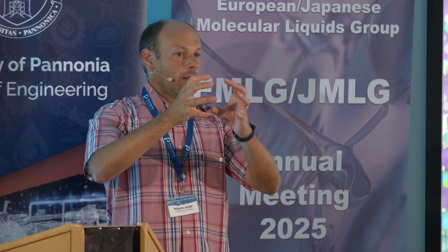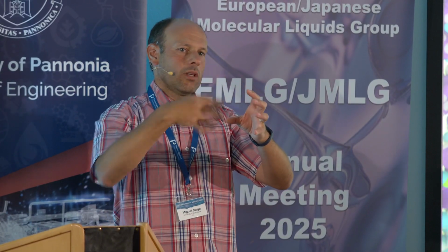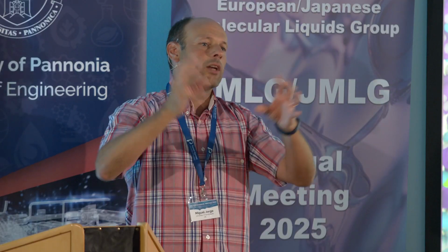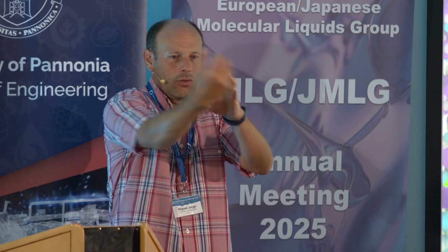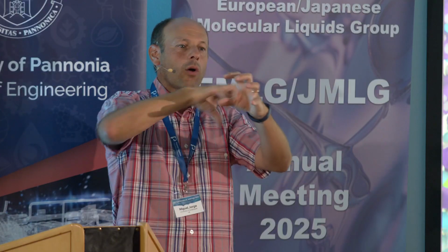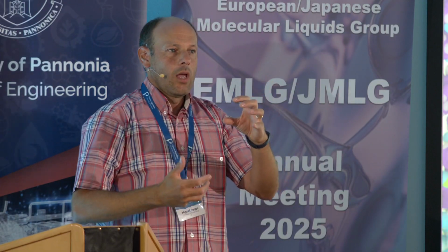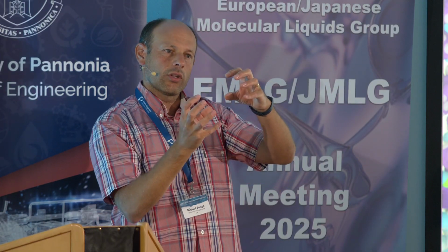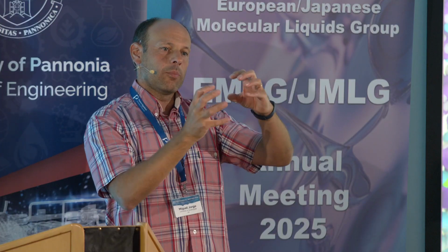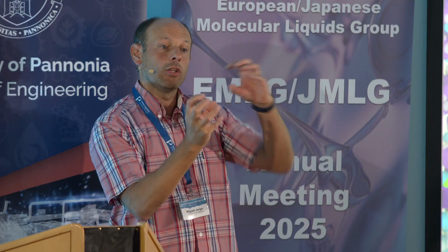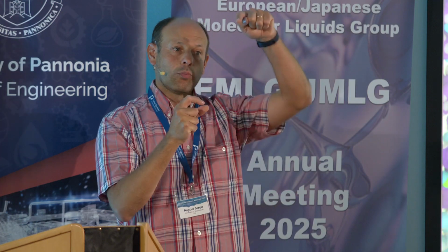Now, if you just do that, you can have up to 8 or 9 coordination, because you can just surround the central monomer with other monomers. So in order to keep that coordination number at 4, and keep the tetrahedral orientation of the silica, we had to put in those virtual patches, which are essentially repulsive.